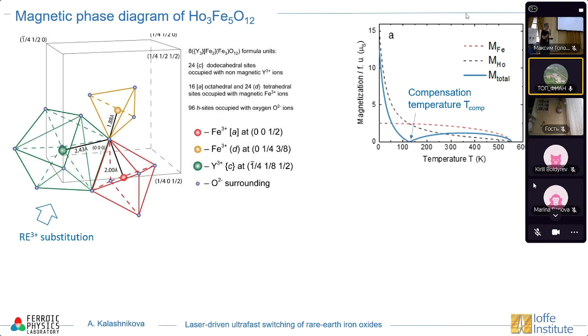So they have net magnetization. What is important, if we replace yttrium by some rare earth in these dodecahedral positions, this rare earth's magnetic moments also order because of the coupling to the iron. In the end, we get this ferrimagnet where we have net magnetization of iron and net magnetization of holmium pointing